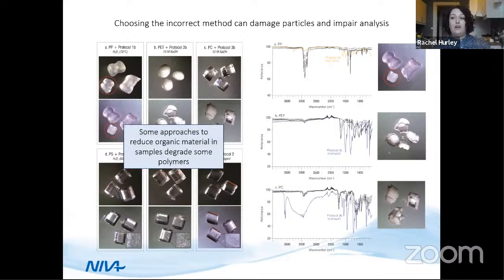This damage can also follow the particles into chemical characterization. The degraded plastics may not register in the same way, and the polymer type may be misidentified. So we can see here that there are some differences in the spectra as a result of these degraded particles. So it's very important to check that protocols preserve the microplastics that you're trying to analyze.